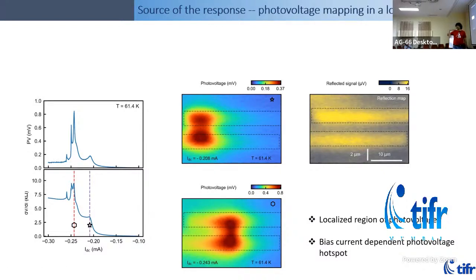Something that we don't fully understand is, if the absorption of light there is any different, it will generate heat and still affect the suppression of superconductivity in space. We don't fully understand it. These are optical images, simultaneously grabbed, of reflection. You can see this is the chromium part, and there is additional scattering from it. So if there is additional absorption, this is certainly plausible. But from the extended films, there is basically no response.